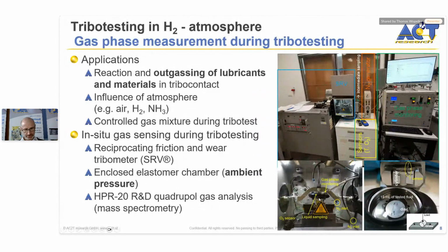But the cool thing is that we equipped this setup with a conventional mass spectrometer, and we can measure the outgassing of lubricants or the reaction products of a lubricant during the tribo test with the mass spectrometer. So this is actually a very interesting topic. It can be run under different gas atmospheres, and we also use the system to control the gas mixture during the tribo test to check if there's any contamination or if there is no explosive gas mixture formed.